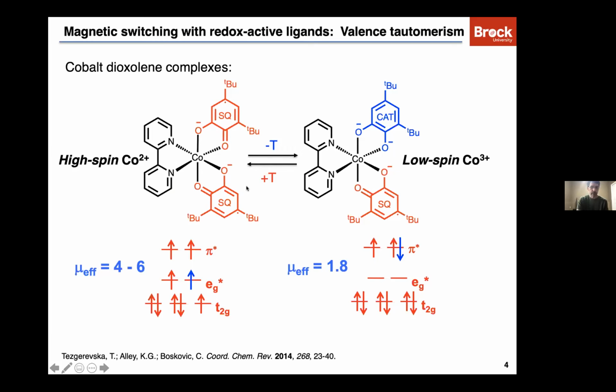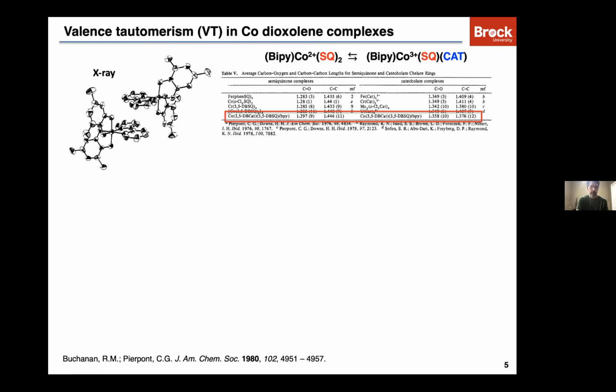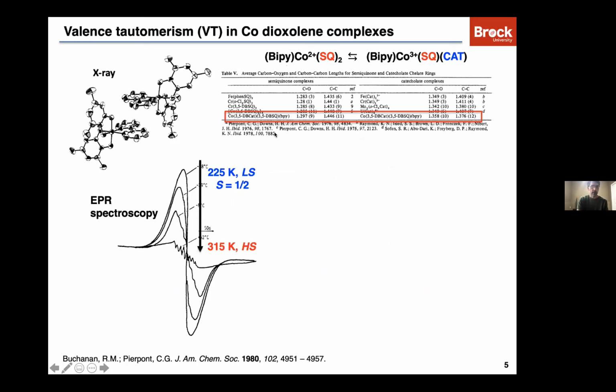Now, these have been studied for, I guess, over 40 years now. This is one of the original papers, Pierpont and Buchanan from 1980, dealing with the prototypical bipyridine cobalt bis-semiquinone complex. Of course, you can track valence tautomerism by EPR spectroscopy, where you see a typical kind of radical spectrum at low temperature. And as you warm this up, you get contributions from the cobalt-2 and line broadening and so on.